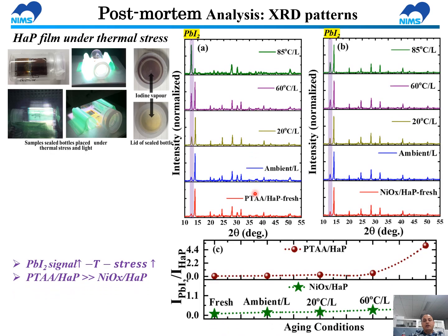And to understand more, we also collected the XRD pattern of perovskite film deposited on PTAA and nickel oxide. We can see the perovskite grown on PTAA with aging increased the PbI2 peak, which suggests that the perovskite film deposited on the PTAA layer degrades much faster, and this also supports the faster degradation trend of the PTAA device. Actually, PTAA itself is denatured when it is exposed to light and heat with aging. That's why it also accelerates the deterioration of the bulk.